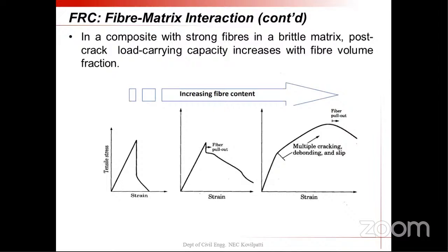And next, fiber matrix interaction is purely based on the fiber content. There are so many factors governing the behavior of FRC, but among those, the fiber content is what I have taken as the main parameter for my investigation. Increasing the fiber content will totally alter the behavior of the concrete. So in the first diagram, you can see it is for zero fiber concrete.